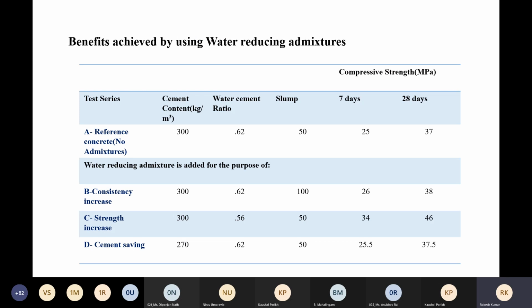Benefits achieved by using water reducing admixtures. Here you see, using this example, it is the one mixture, that is a reference concrete. Cement content 300 kg per meter cube. Water cement ratio is 0.62. Slump required is 50. 7 days strength 25 MPa and 28 days strength is 37. That is your reference concrete.